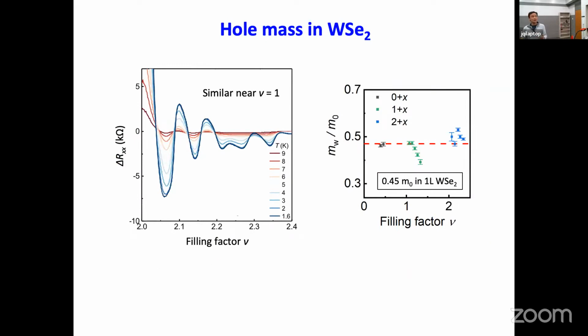So now the gap survived, you may also ask, what is the mass of the itinerant carrier? We can do a temperature dependent quantum oscillation measurement. And it turns out that the mass is about 0.5 electron mass. And you can compare to a monolayer of tungsten selenide electron mass, which is 0.45. So you can actually see that in this particular system, for some reason, the tungsten nearly does not see the Moiré potential. It's like nearly just free carrier or itinerant carrier in the tungsten layer. But only the MoTe has the strong Moiré potential that produces a lattice of local moments.